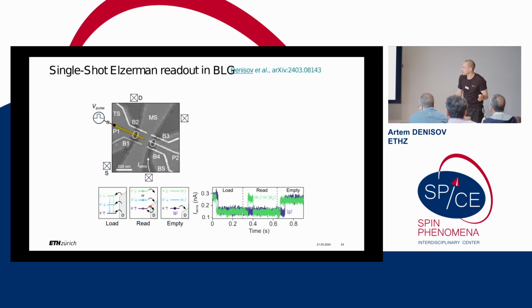In order to do this, we fabricated a device which has not a single quantum dot, but two quantum dots. One serves just as a charge sensor, which is capacitively coupled to the main quantum dot, and which serves just to monitor as a function of time the occupation of the dot. And in contrast to just simple spin qubits, we have more excited states. We have three excited states. I'm going to talk about only the two lowest of them. So with more excited states, we have more possibilities to put our readout level between different states to actually probe different types of relaxation from different excited states. But the process experimentally is the same. We will just count the number of times we have a blip in our sensor signal, like on this green trace, compared to the situation when we don't have a blip, like on the purple trace, and just plot the probability of it.